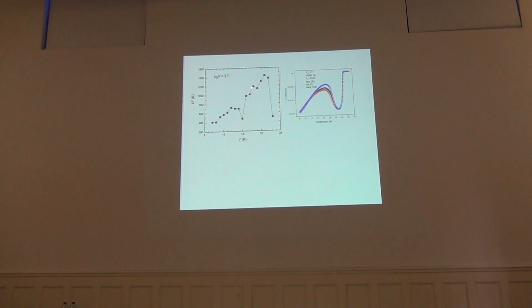Other measurements have been done at 3 Tesla, and again we have some interesting differences. And you see this is the 3 Tesla AC measurement, and you can find some correlations between these curves here. But as I said before, the magnetic relaxation measurements have to be completed and repeated and made for many more temperatures to get a conclusion about what type of vortex dynamics we can imply for this interesting anomaly in the vortex dynamics in this type of single crystals.